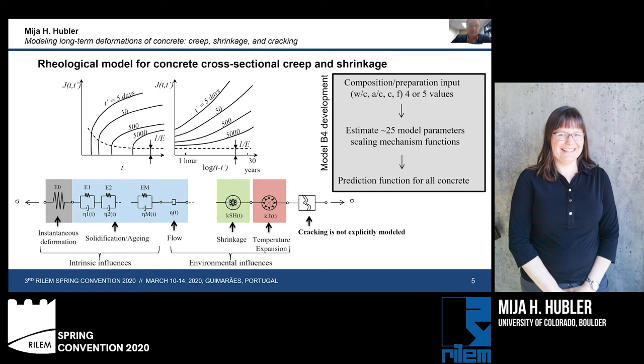Okay, so let's talk a little bit about theories out there. Many theories are based on rheological models for the concrete cross-sectional behavior. Here I have illustrated an example compliance function. The shape of the compliance function varies with the time of loading, and we can plot it in terms of the time, the age of the concrete, as well as the logarithmic age of the concrete.